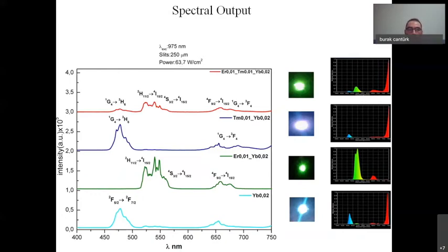After the characterization analysis, let's proceed with the optical outputs. This is the luminescence analysis of the single-doped, co-doped, and tri-doped phosphors in the range of 400 to around 800 nanometers under laser excitation, which is our excitation source, at a constant, single pumping power. And here we see the cases where ytterbium, erbium, and thulium, all of the dopants, are together and compared.